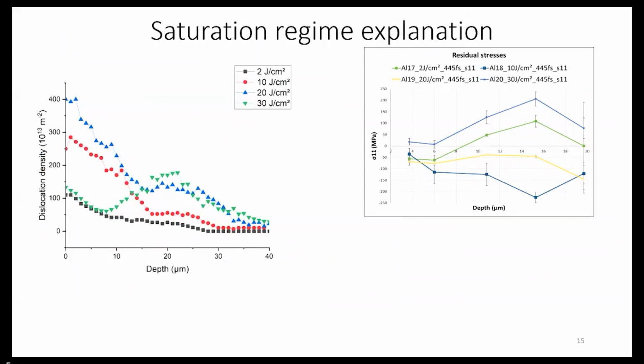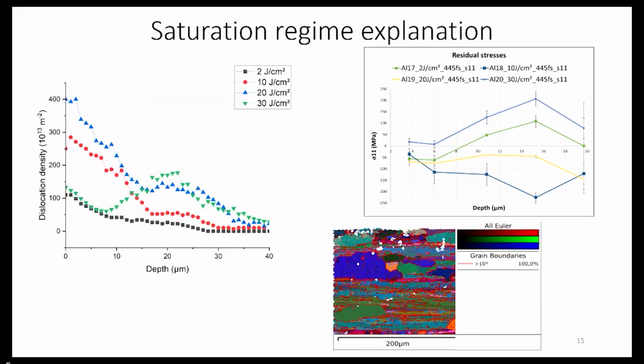So this made us think that this could come from a recrystallization which occurs at the surface. And to confirm that, here's an EBSD map done just below the surface of the irradiated sample. So here is the irradiated surface, and you can see that there are some big grains everywhere here, and these are coming from recrystallization, because as I prepared the material, it should be coming from the cold work.